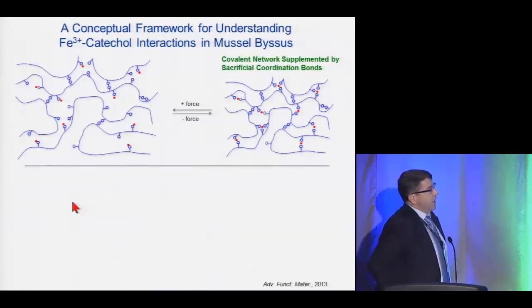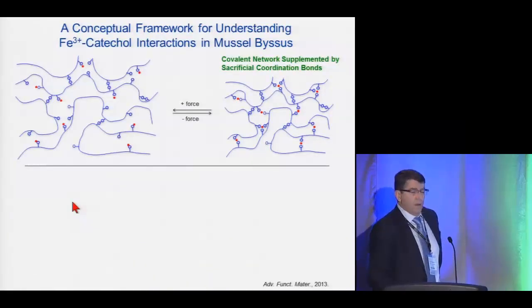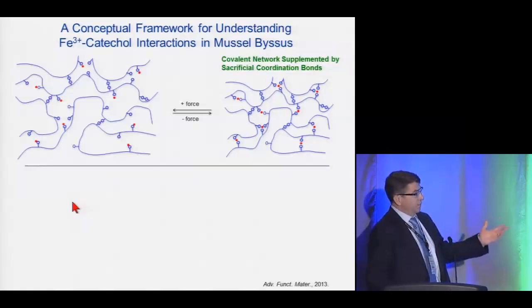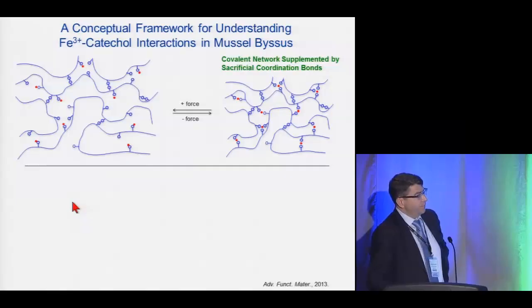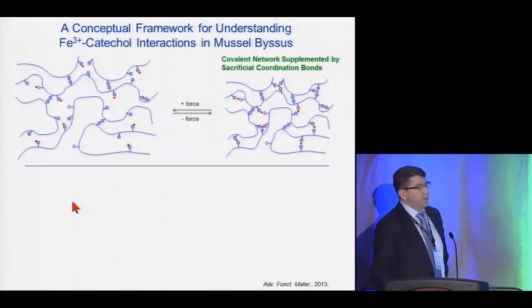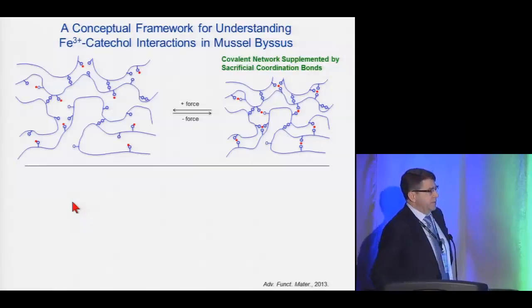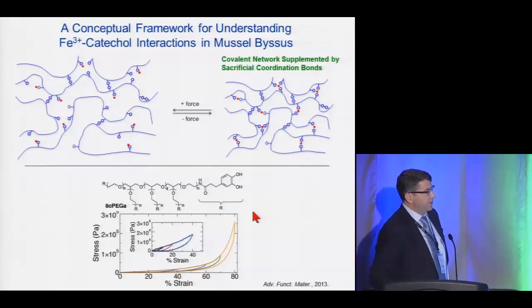And this has led us to recently propose a rather complicated formalism for the role of iron and catechol in the system, which essentially gives rise to a cross-linked protein matrix that's cross-linked both by covalent bonds as well as these coordination bonds. And under applied force, these coordination bonds are actually labile. They're sacrificial in a sense. They can be ruptured under applied force and then reform in the absence of load. And this we showed in actually a synthetic polymer system. This is where a synthetic biomaterial can actually help us understand the biological system.